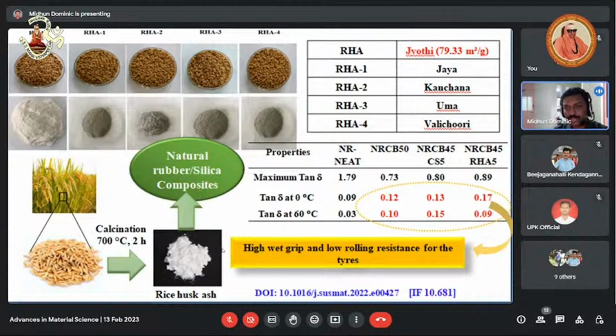We found that the rice husk ash obtained from the Jyothi variety has a higher surface area, around 79 meters square per gram. We incorporated this rice husk ash derived from the Jyothi variety along with carbon black. We replaced 5 PHR, or 5 grams, of carbon black with 5 grams of rice husk ash.